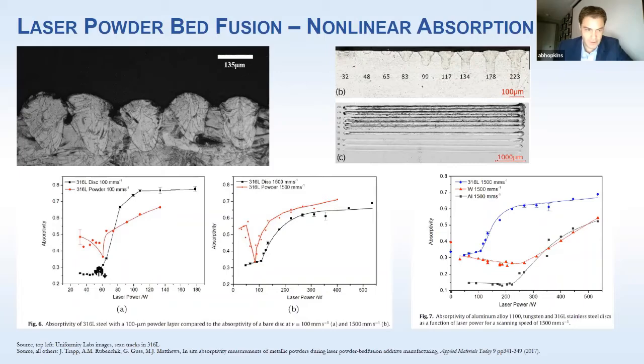Pardon me. You can see absorptivity peaks once you're drilling a deep hole. Once you're drilling a deep hole, the laser is absorbed in the center of the pit and then scatters into the sides of the hole. And so you lose very little laser power to scattering. However, when you're not very deep, you're scattering about the build chamber. And then here's in 316L powder.